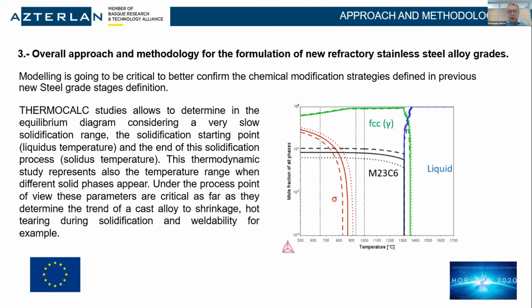Well, we can take a look to the right, and we can take a look at the phases generation. For example, we are representing the phases generation, the liquid, how the liquid is transforming into different phases, and at which time, at which temperature they are being generated. And we have in dashed lines the variation when they appear or not, depending on different ranges of the chemical composition of the alloy. So we can see that it helps us to manage very well the effect of this chemical composition on solidification ranges, on appearing of different phases.